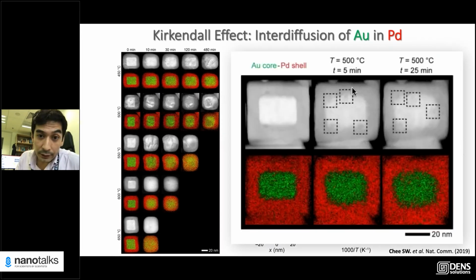But if you look at the STEM images carefully, right? You see voids forming at the interface between these two metals, here, here, here. I don't know if the contrast is good enough for you to see it, but the voids are forming. This is information you cannot get from simple diffusion measurements, but since we are monitoring, we can measure the bulk property like interdiffusion, and we can also see what kind of structural changes are happening in the material.